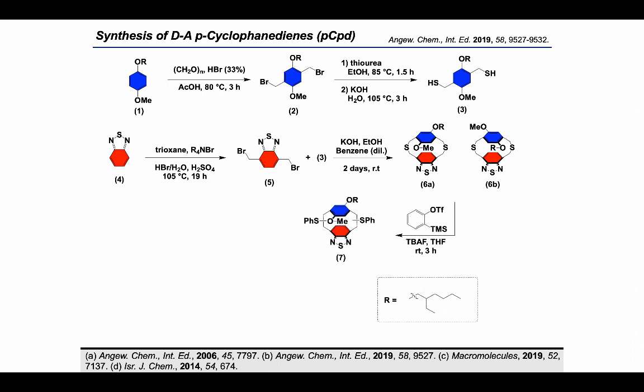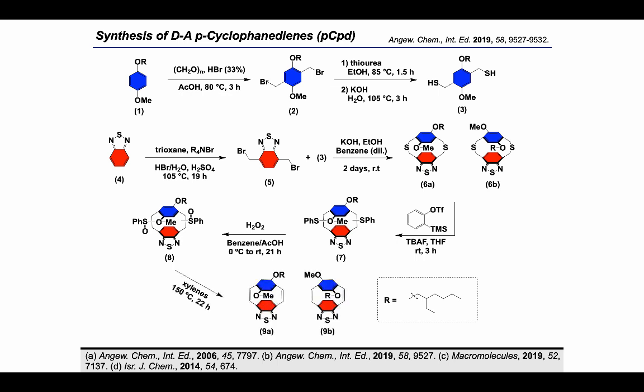Next, we carefully generate benzyne in situ by slowly adding tetrabutylammonium fluoride to a solution of molecule 6 and a trimethylsilyl triflate to induce a Stevens rearrangement. This step forms the desired carbon-carbon bond, and by oxidizing the resulting phenyl sulfide with peroxide to make it a better leaving group, we then heat it to 150 degrees Celsius in xylenes overnight to achieve the desired elimination of the 2 isomers as the final monomer.